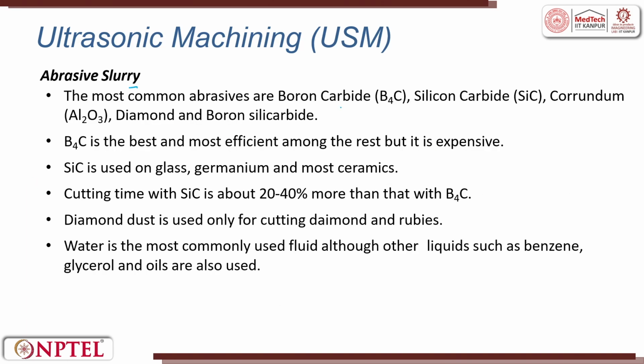Slurry concentration, we have seen boron carbide, silicon carbide, then you have corundum, alumina, diamond, boron silicon carbide; all these things can be used. The best one we use is always B4C, which has a very high hardness, and here since the temperatures are not very high, the boron carbide does not dissociate. So, we use boron carbide as the material here. Silicon carbide is also used on glass. The cutting time with silicon carbide is about 20 to 40% more than that of B4C. Diamond dust particles also can be used. Water is used for making the slurry.